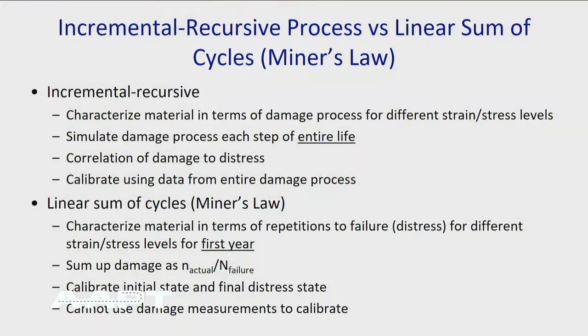With Miner's law, which was actually what we used in our precursor to this, we basically characterize the material in terms of repetitions to failure and end state. And then we look at potential paths to that end state, which occur across the first year. And we get our big N's from that, and then we estimate the little N's, the traffic that's coming, and look at that damage ratio. And then we have to calibrate to the end state. To be able to calibrate Miner's law, you have to have carried every one of your sections to the end state, because otherwise you don't have a data point. You have a right-hand truncated data point. So one of the other things we knew from our APT is not all of our sections failed. Not all the WestTrack sections failed. Not all of our APT sections failed. But we can still calibrate the damage process on every single section without biasing our data set by eliminating those that didn't get to the final cracking end state.